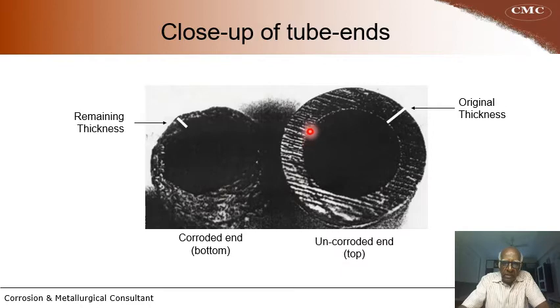And you can notice the inside diameter is very uniform. Inside surface is very uniform. You can see the inside surface here also uniform, whereas the outside surface is very smooth on the uncorroded end, whereas on the corroded end, outside surface is very rough. This indicates that corrosion has taken place on the outside surface. And you can recall the outside surface contains boiler feed water, whereas the inside surface contains hot gases. So this indicates there has been some corrosion problem on the outside surface. That means the boiling water.